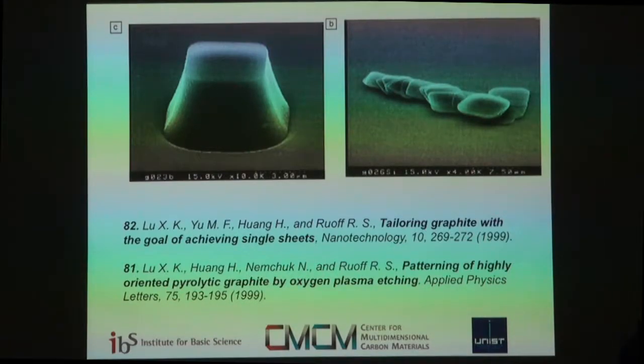And then we spent about a year with Michael Lerner's group at Oregon State University, because he had been making graphite intercalation compounds with perfluoroalkyl cations and lifting the layers apart to about 1 to 1.5 nanometers, extraordinary. And so it seemed to me that if we could do that with these sorts of pillars, then we'd probably get individual layers. And it never worked. It was quite remarkable. If you take graphite, it works beautifully. But if you take these pillars, it doesn't.